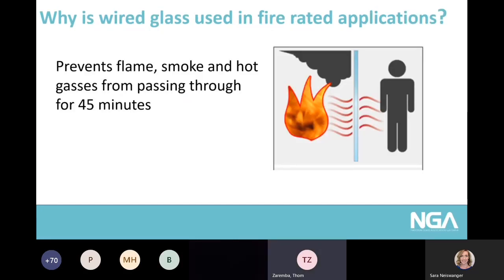Wired glass is used in fire-rated applications primarily because it prevents flame, smoke, and hot gases from passing through it for 45 minutes in a fire test. And I don't know how many of you know the details of fire tests, but in a 45-minute period, a fire test will expose the glass to temperatures in excess of 1,000 degrees Fahrenheit. Next, please.